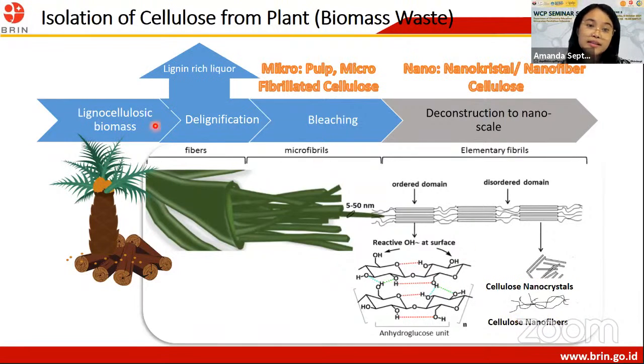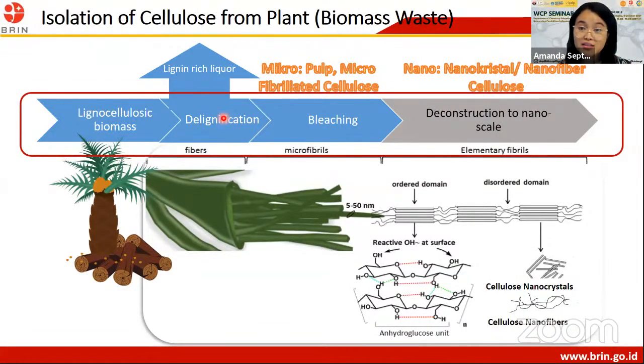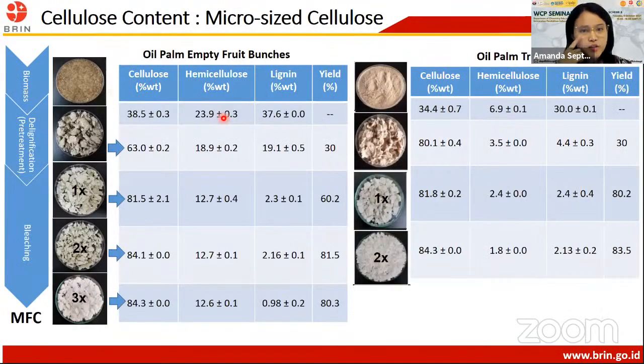And also, during the delignification process, we can get lignin-rich liquor, and from this lignin-rich liquor, we can also derive several materials. But my presentation will be focused on the cellulose itself. So regarding the cellulose content after the processes, we can see from this table, for example, that we derive cellulose from oil palm empty fruit bunch and oil palm trunks.